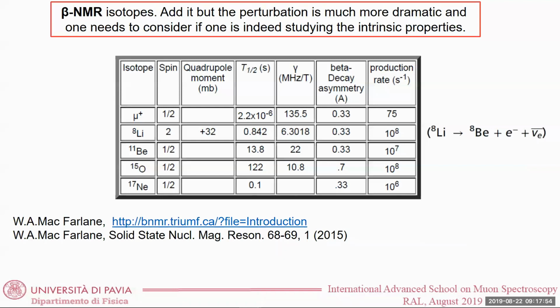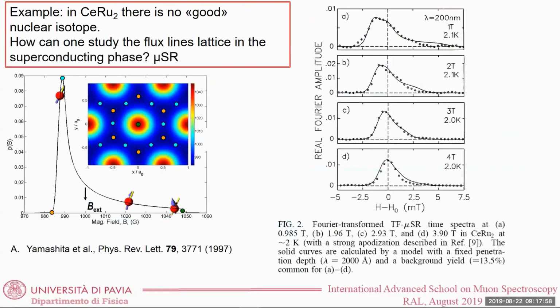Suppose we do not want to perturb our system and we don't have a good nucleus. What we can do is MUSR. For example, in this system, cerium and ruthenium are not good nuclei. If I want to study a superconductor, the flux line lattice, as you have learned from Roberto De Renzi, when you enter the superconducting state, if it is a type 2 superconductor, you have flux lines entering, and if the field is applied along this direction, there is a modulation of the internal field which gives rise to a distribution of the field inside the sample. There is then a broadening of your MUSR spectrum. You can measure your spectrum by taking the Fourier transform of your MUSR signal in transverse field, and then study, for example, the temperature dependence of this broadening, which is associated with the temperature dependence of the London penetration depth.